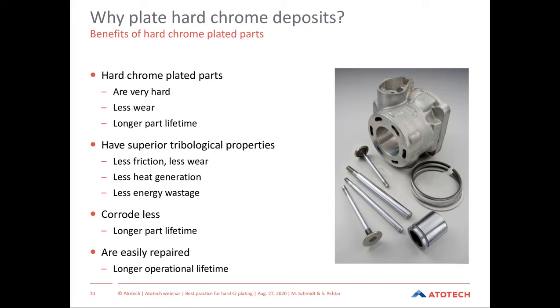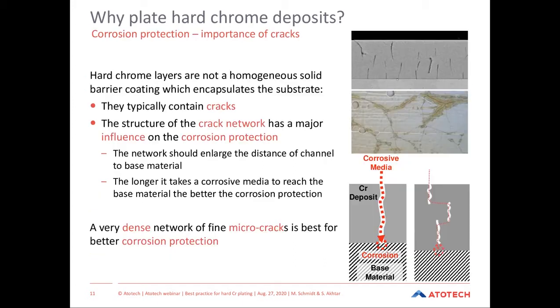Number two, hard chrome deposits impart superior tribological properties to the component, such as low coefficient of friction, high hardness, which gives rise to high wear resistance, and high corrosion resistance. One of the characteristics of hard chrome deposits is the formation of cracks within the coating, and these cracks provide important benefits. So let's look at how these form within the coating.